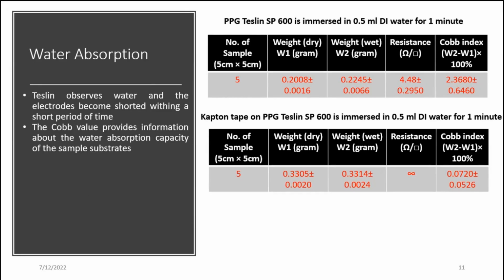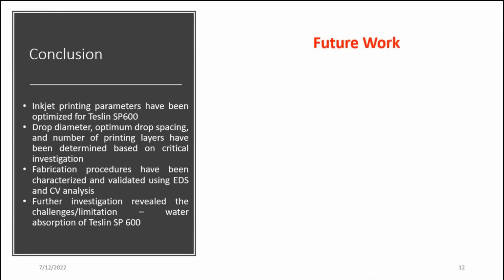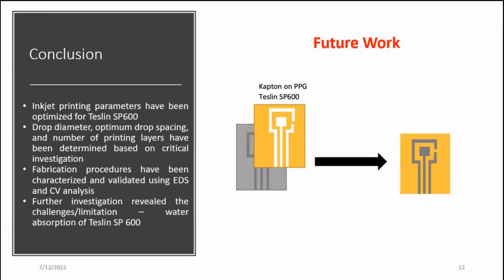So how to solve this issue? Because the existing technology offers coating the substrate, we didn't want to do that, because that's how we compromise the adhesion of the printed pattern on the substrate. So our Kapton definitely works, but we need to figure out a way to maintain the adhesion plus get rid of the water absorption problem.